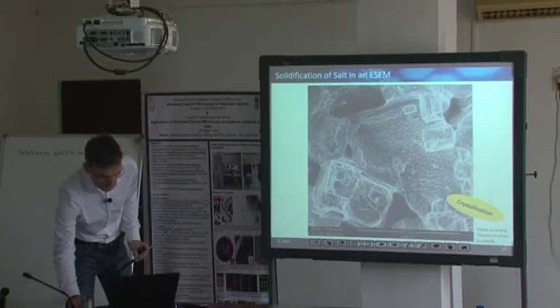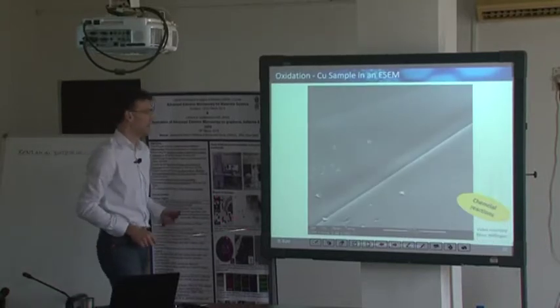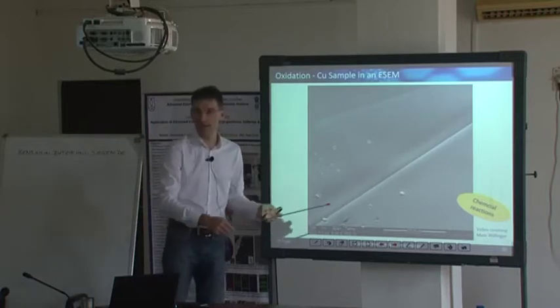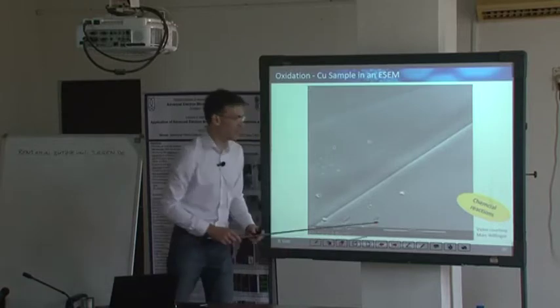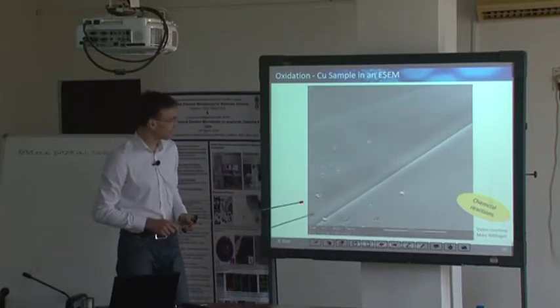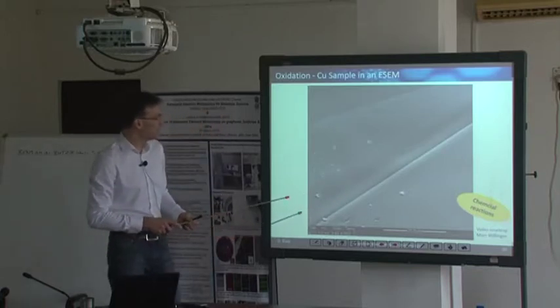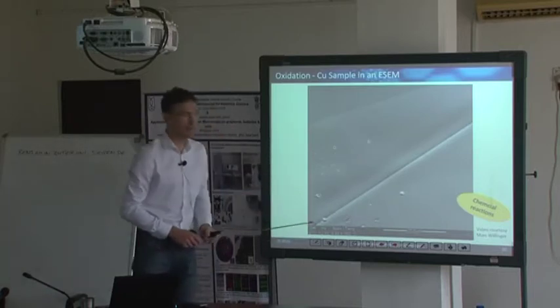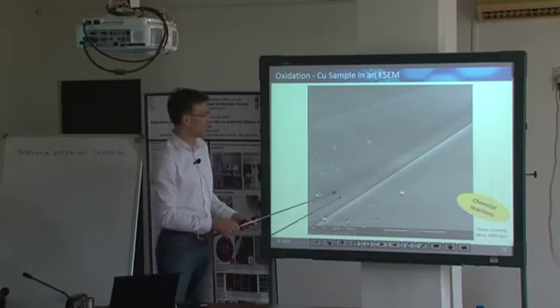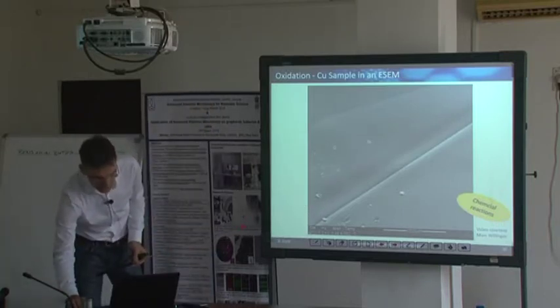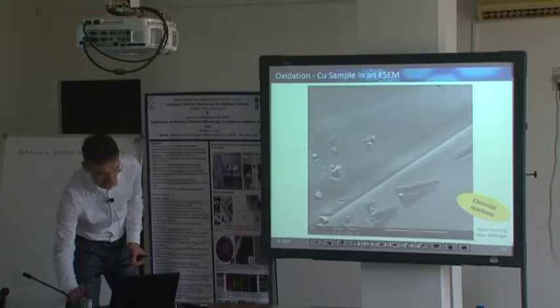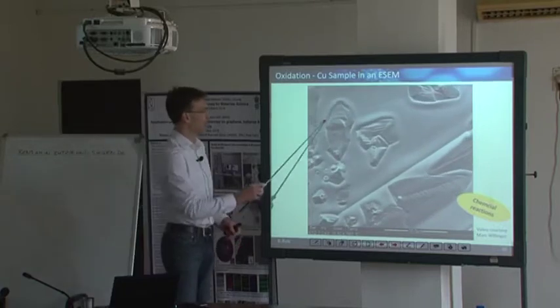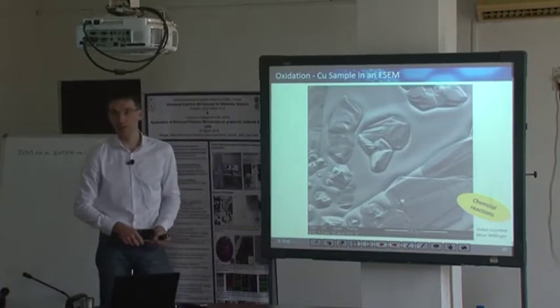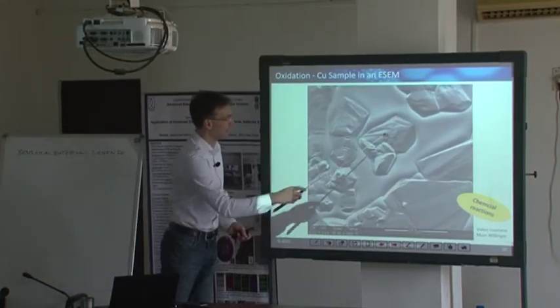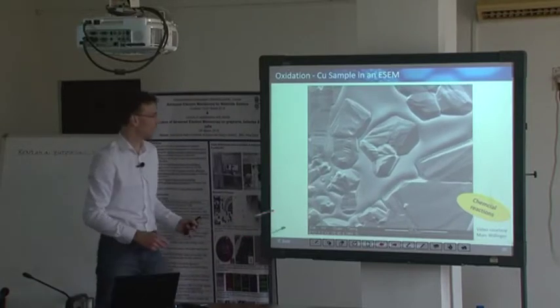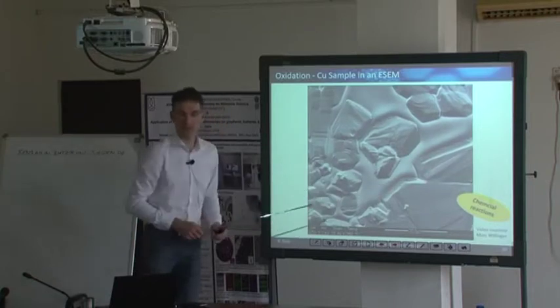There are two more examples which are more relevant in applications. This is a copper surface, a very nice and clean sample, and I got these from a colleague from Berlin, Mark Willinger. These are not published, but nonetheless I would like to share them here. This is a copper surface in an oxygen environment at slightly higher temperature, so it is about the oxidation of a metal. You will see that it does not happen all over the surface. This is the copper oxide that forms on the surface, in secondary electron imaging mode, and you see the nice growth of all those copper oxide crystallites. In this particular case, up to that state, not the whole surface is oxidized.